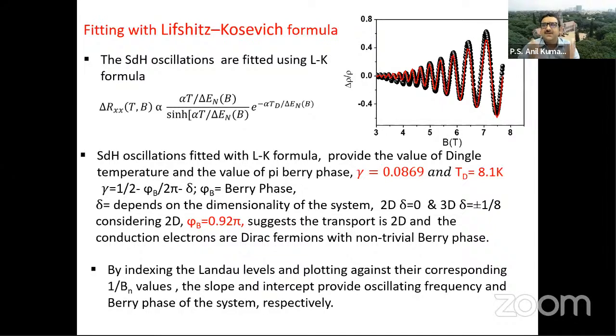Now again, these oscillations we can also analyze by different methods suggested by different people. For example, we can use the Lifshitz-Kosevich formula to analyze these oscillations and extract the Berry phase in this material. And what we are getting in this particular system, putting in all the approximations that are important for this system, is a Berry phase of approximately pi.